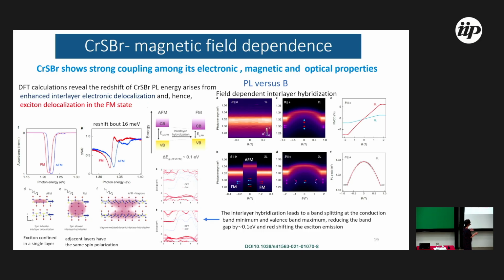Very low field. Here I think it's 0.1 more or less, but it depends; for bulk it is 0.3 Tesla. And you apply a parallel field aligned with the B axis, which is the easy axis. If you apply it perpendicular, you need more field to have this spin canting up to the saturation field. So we can say a ferromagnetic state induced by magnetic field. And this is optics, so it's very easy to measure. You just need the possibility to measure photoluminescence, and photoluminescence can probe the phase state of the material.